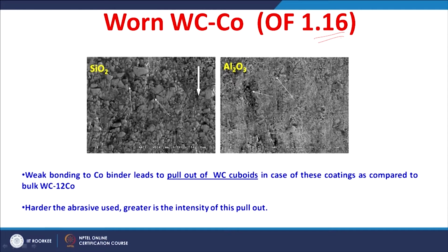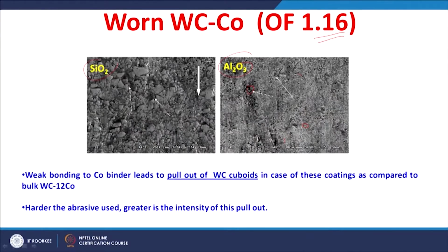You can see there is a change in the mechanism from what we saw in the bulk material of tungsten carbide cobalt. The weak bonding of the tungsten carbide to the cobalt leads to easy pull out of these tungsten carbide cuboids in case of coatings as compared to the bulk tungsten carbide cobalt. And with respect to the effect of abrasive, the harder the abrasive, the greater is the intensity of this pull out. So, you can see a lot of pull outs in case of the harder abrasive.